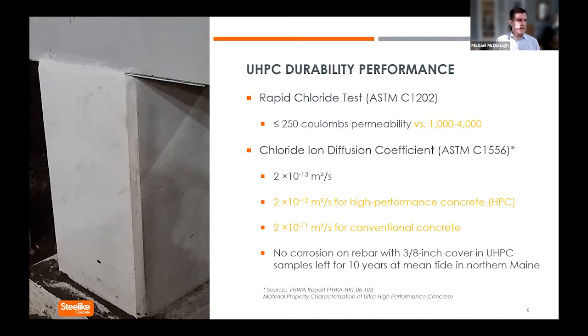And this is not just all theory. This has actually been proven in the field by a project where samples of UHPC were left at mean tide in northern Maine off the coast for 10 years and longer. And UHPC samples that were in this environment after 10 years and 15 years were pulled out. Rebar with only 3/8 inch cover was extracted, and the rebar showed no signs of corrosion.